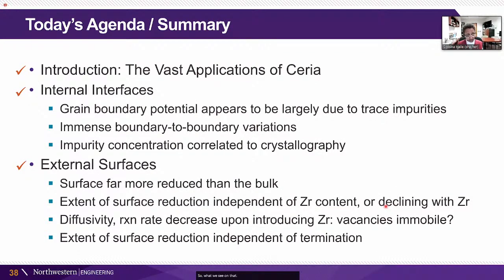What we see on the external surface is that the surface is far more reduced than the bulk. That's consistent with predictions, but it's either independent of zirconium content or declines with zirconium content, the opposite of what one expects. The kinetic parameters are penalized when we introduce zirconium, and we speculate that's because the vacancies are immobile. The reason that there are more vacancies is because zirconium wants to have a lower coordination shell. And so those vacancies are stuck there right next to this zirconium. And again, the extent of surface reduction appears independent of termination. And so there must be other reasons why these different size controlled catalyst particles have differences in catalytic activity.